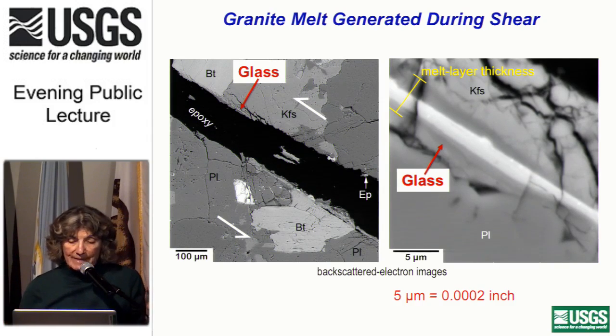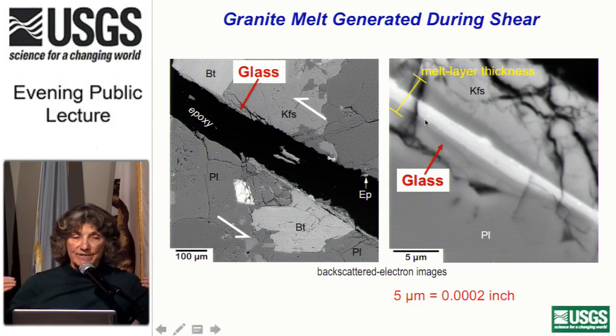So the maximum temperature that was reached in the melt was perhaps at least 1500 degrees centigrade during this slip event. And we use the peak temperature, and also the average thickness of the melt layer, in calculations of the energy budget during that slip event.